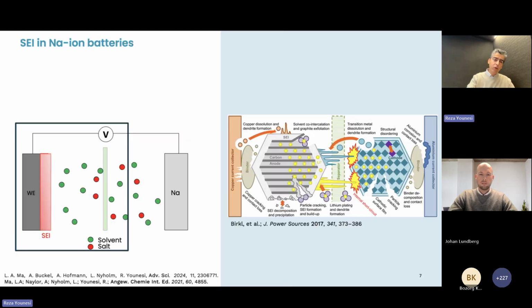This is what we have been trying to understand in sodium-ion batteries, and to see how different that is compared to lithium-ion batteries. What you see on the left is a model system that we have been using to evaluate different electrolyte chemistries. You have a working electrode, which could be a foil, like platinum or gold foil, or it could be glassy carbon. So there is no intercalation into this electrode. We use this type of model system to simplify the aging mechanism and to understand each aging mechanism one by one.